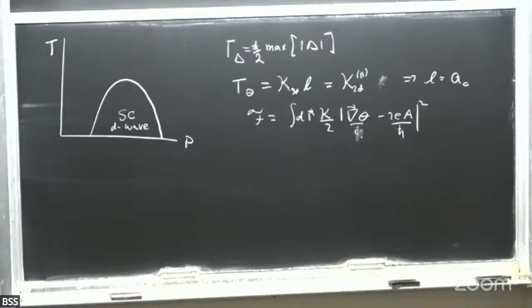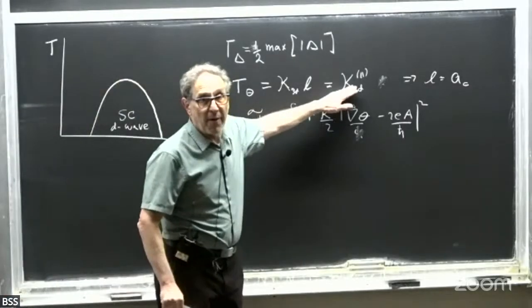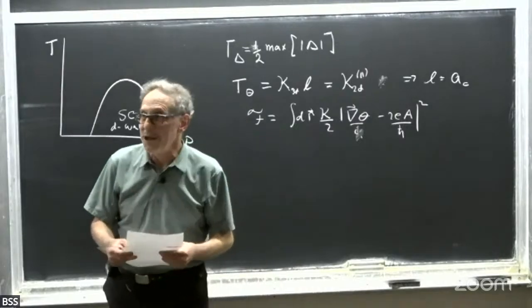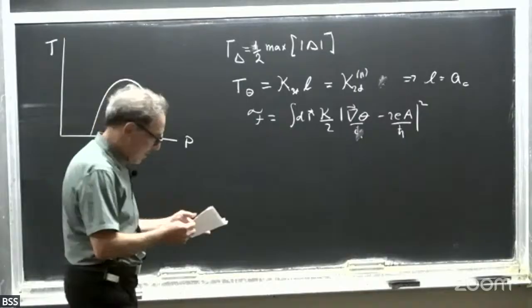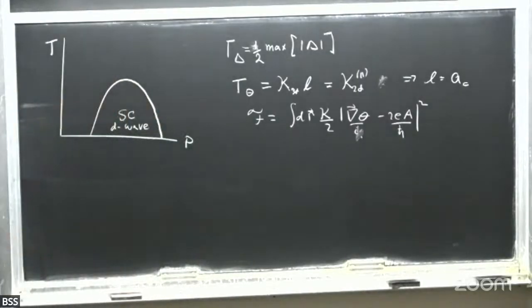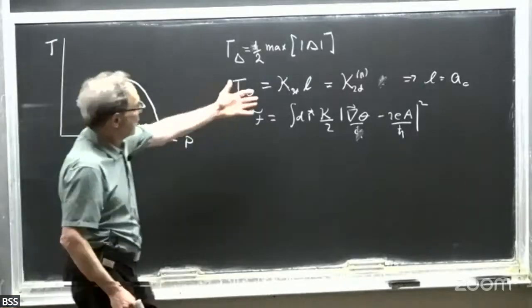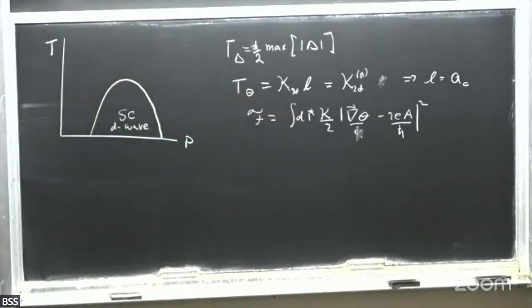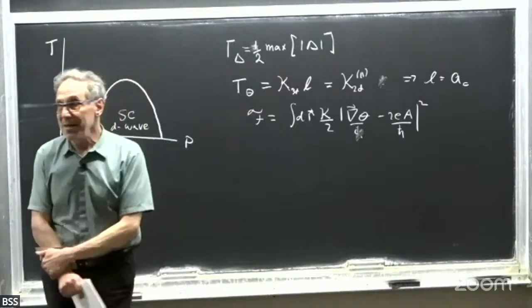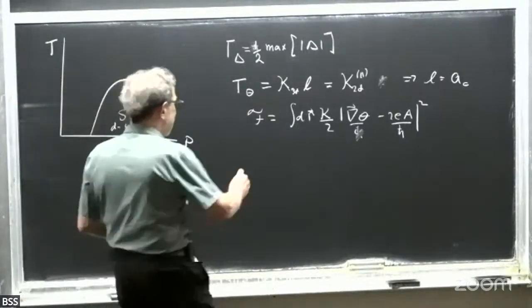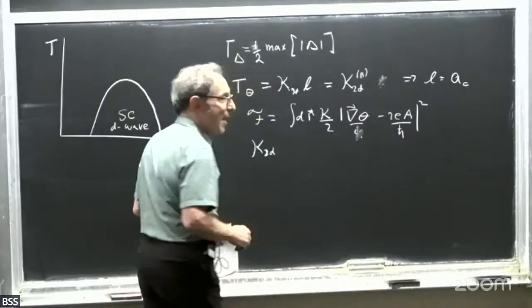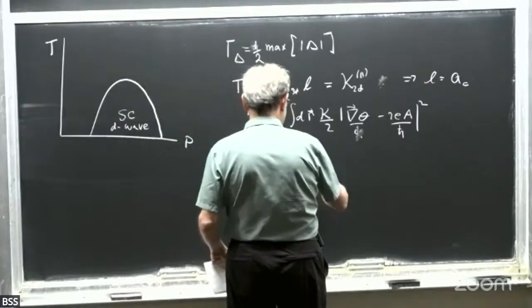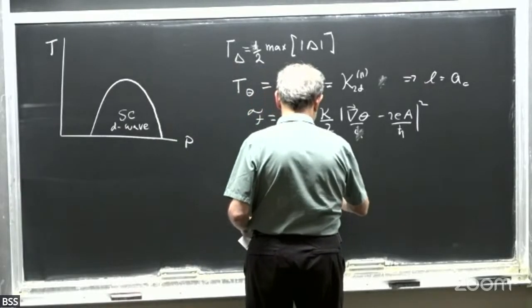In usual superconductors, this scale is very large. Let me just do some dimensional analysis to give you an idea. So I'm here using zero temperature data to predict Tc. So in this case, kappa is the zero temperature stiffness. Of course, kappa is temperature dependent. It must vanish at Tc. But here I'm looking at zero. So let me stick to 2 dimensions. So kappa 2D, I can think of this as being h bar squared over twice